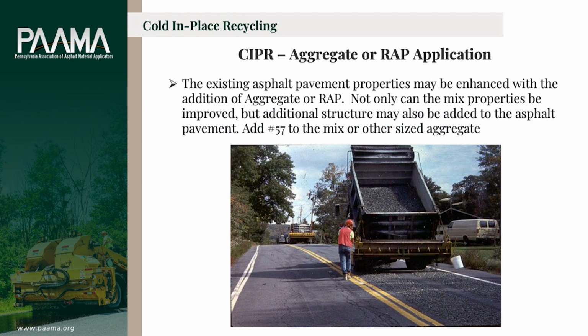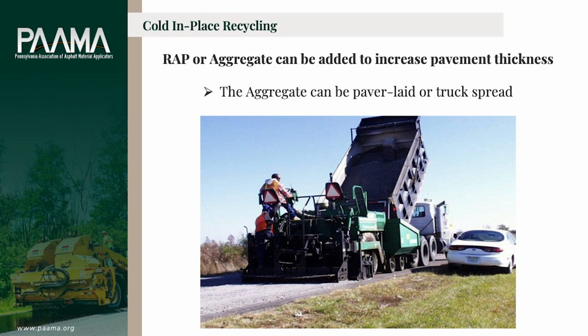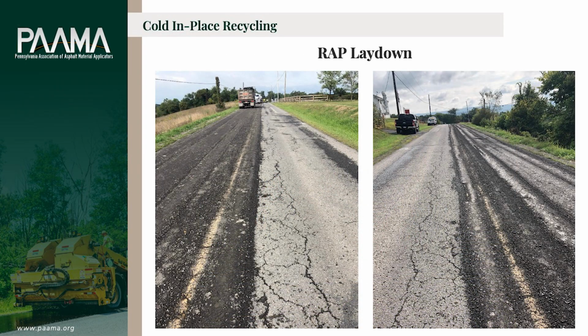Sometimes we need to put corrective aggregates in. If you've got a roadway that's all chip seals, it's all fine material, we may need to put some 57s down and mix those in with the recycle to give it more of a binder type of material back. They can be either out of the rear of a dump truck, or we could paver lay them depending on the thickness of the material that needs to be added. RAP material and millings can also be used, spread on the roadway. We normally compact them down before we start recycling through them.